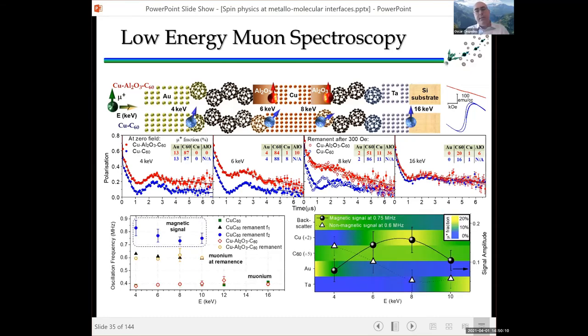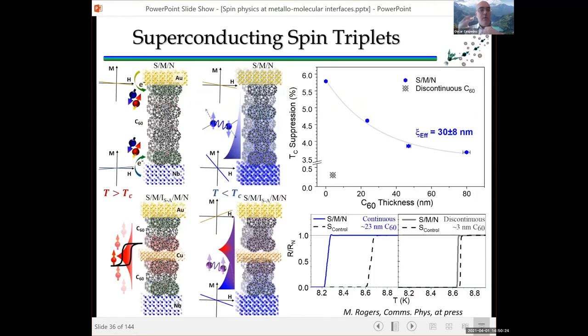Now, this emergent magnetization is very weak. So what can we use it for? How can we detect it? Our idea was to then use this in combination with superconducting samples. So what we have is a superconductor with C60 and then a superconductor with this emergent magnetic copper C60 interface that we call a spin converter.